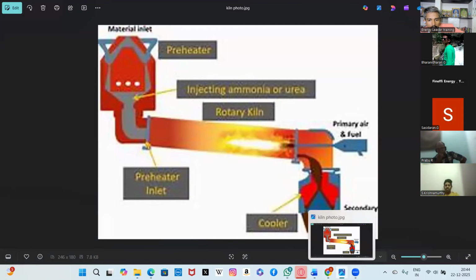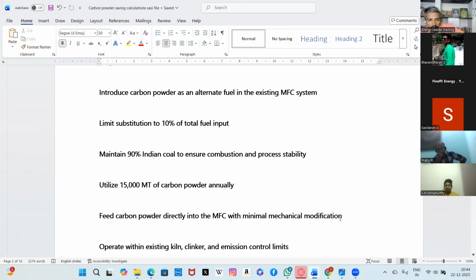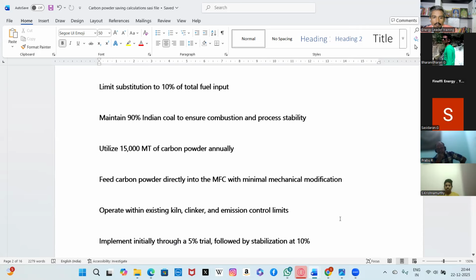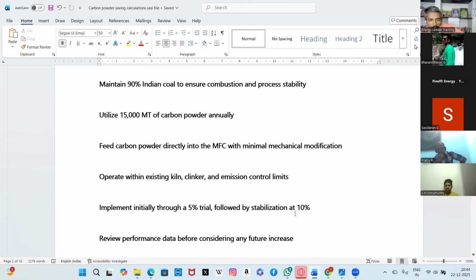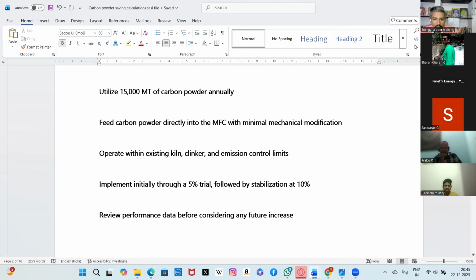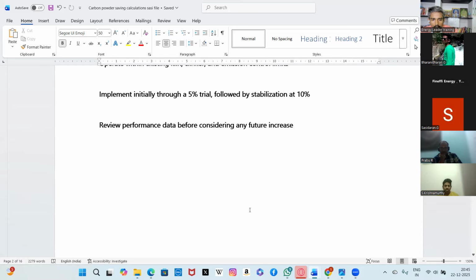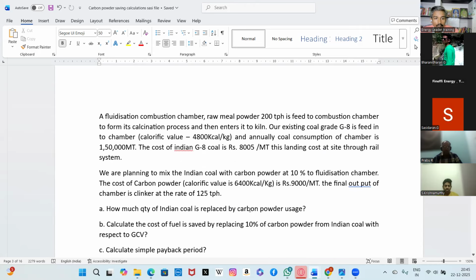So we are planning that both the kiln and fluidization chamber can be supplied with carbon powder. I am trying to combine both as the 150,000, which is annually consumed. In that, I am taking only 10% carbon powder to be mixed with the Indian coal, and how much savings will I get? So that is the proposal I have made. Carbon feeding is today's cement plant alternative fuel which boosts the Indian coal, reduces the consumption of Indian coal, and does not affect our production parameters. Okay. First trial I am trying with 5%, and later on we are going for 10%. I have the calculation for the 10%. The explanation part is coming below.